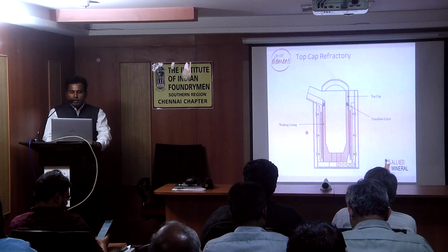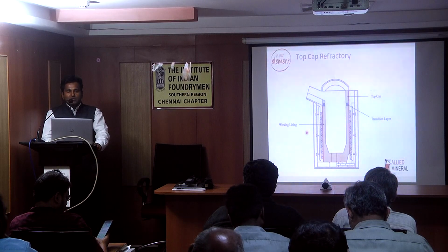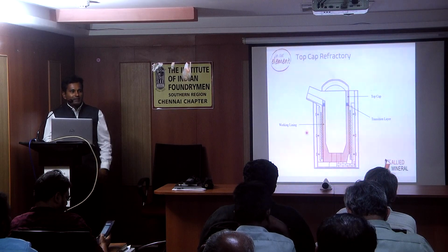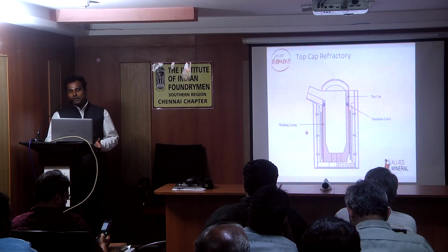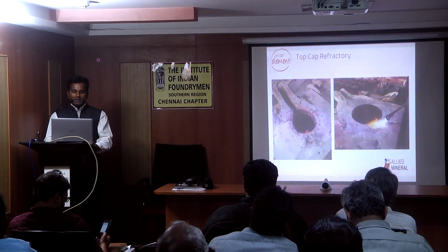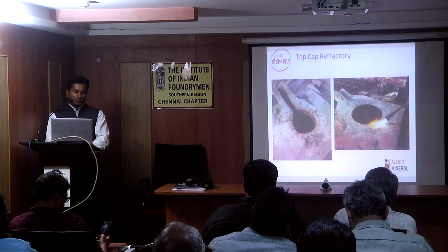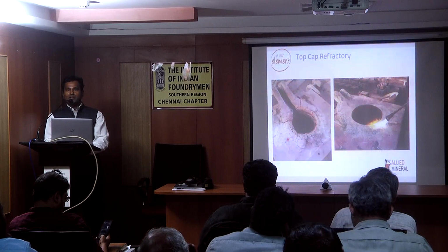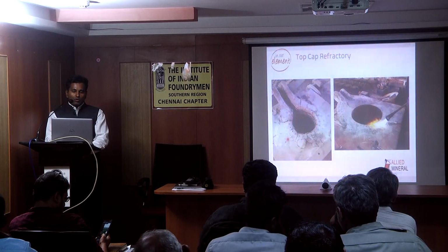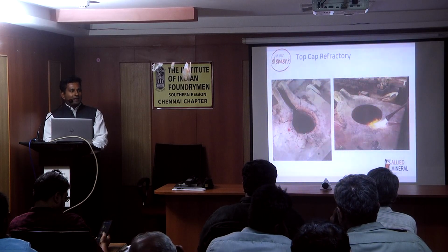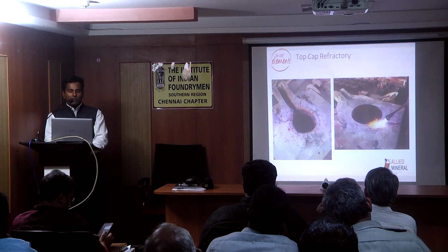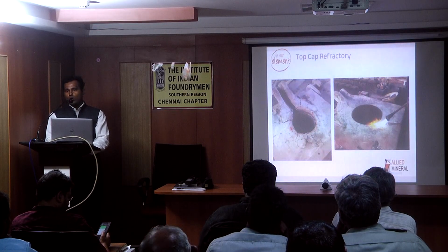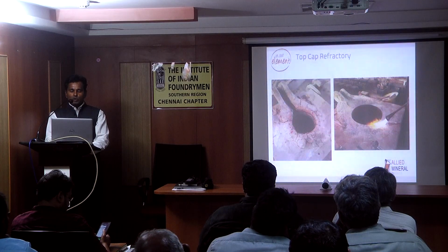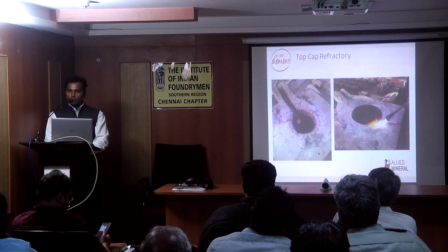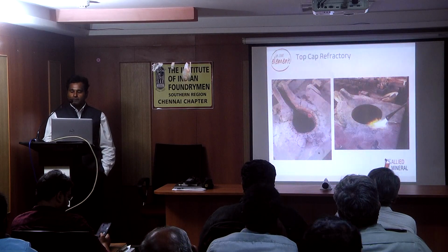And another aspect I would like to cover is top cap refractory. People used to do it the same way as we dealt with the spout refractory. I've given a couple of examples. This is how generally the maximum of foundries will have the top cap. They use the main working lining with some binders and try to form a heap on top of your top block, and because of the thermal shock from top to bottom, there will be a lot of cracks in this extended top cap.